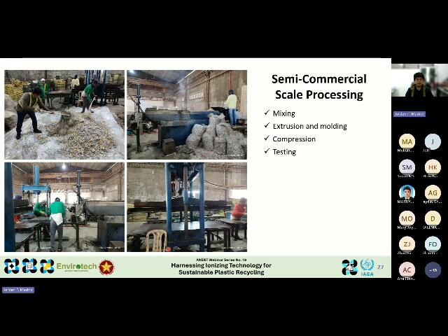I'd like to show some photos taken during the production runs at Envirotech. This gives us a clear picture of how the samples were actually extruded and compressed at a larger scale. The process begins with plastic waste from Envirotech and irradiated plastic waste at PNRI. They are manually mixed to ensure initial blending of the two types of plastics. After that, the mixture is fed into an industrial extruder, where the plastics are subjected to elevated temperature and mechanical shear, causing them to melt and mix thoroughly at the molecular level. Once the molten blend is prepared, it is molded and compressed into the desired shapes. The exact shape depends on the type of test we want to perform afterward, for example flexural testing, compressive testing, or other mechanical and physical characterizations.